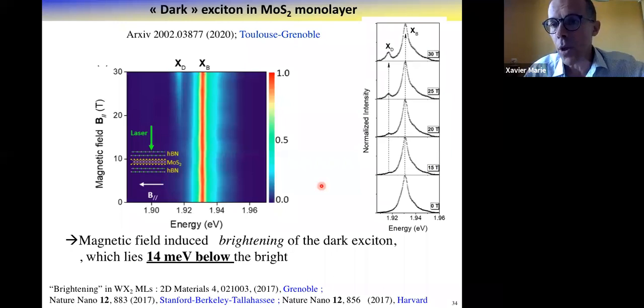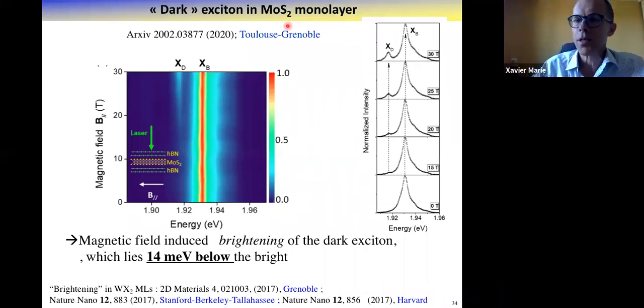than the bright exciton. And indeed, in time resolved luminescence, we find 1 nanosecond, whereas for the bright exciton you have 1 picosecond. But indeed, we could perform this experiment in time resolved experiment, in fact we plan to do it, not on MoS2, but on MoSe2. I have not presented it, but in the same paper, and also there were nice results in Tallahassee, the dark exciton has been identified on MoSe2.